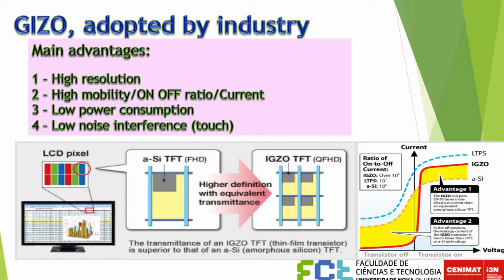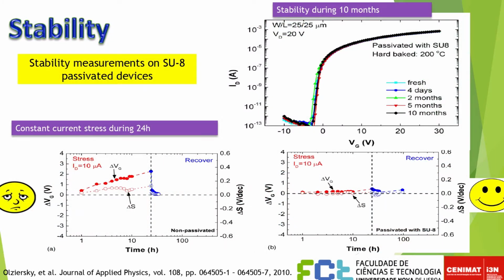So, if you want to sell your product or your service to an industry, you need to take care of three main properties. The first one is related to stability. For example, here we performed some tests where we measure the different electrical characteristics. This is a typical IV characteristic of a thin film transistor, of a field effect device. Here we measured the first one, but even after 10 months, the device is quite stable. So the electrical performance is exactly the same. And also here, in that case, the device was passivated with a specific polymer.